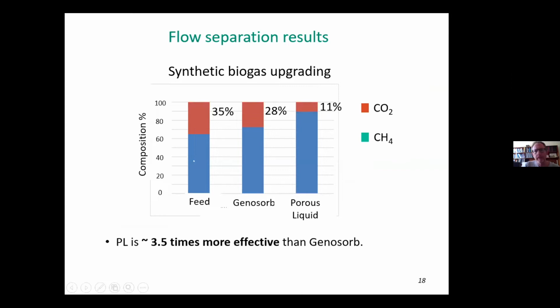So here, these are the data from the continuous flow rig after a single pass of the solvent through. This is the feed gas which is going in. So this is meant to mimic biogas. We have mainly methane, 65%, 35% carbon dioxide. Using Genosorb as your solvent to extract out the carbon dioxide, after one pass through the system, the CO2 goes down to 28%. So 35 to 28, that's good, it's working, it's doing its job. But you see what happens with the porous liquid. Now the CO2 content goes down to 11%. So it's much more effective.